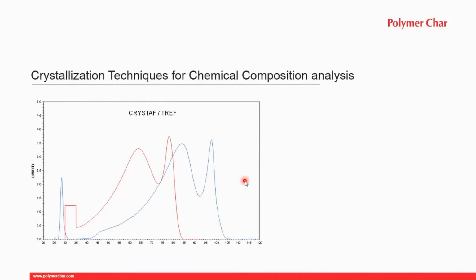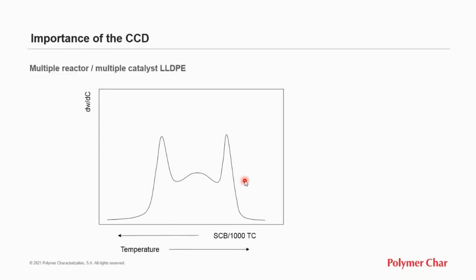Okay, so let's change topic now to crystallization techniques. Those are used specifically to study the chemical composition distribution, CCD. This CCD, in many cases, is a more discriminating feature than the molar mass distribution. Chemical composition distribution is measured on a temperature scale by crystallization techniques. And in the case of polyethylene, the temperatures are related to the number of short chain branches. Short chain branches reduce the crystallinity and so reduce the crystallization temperature.